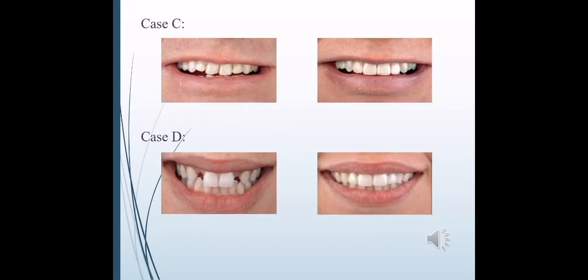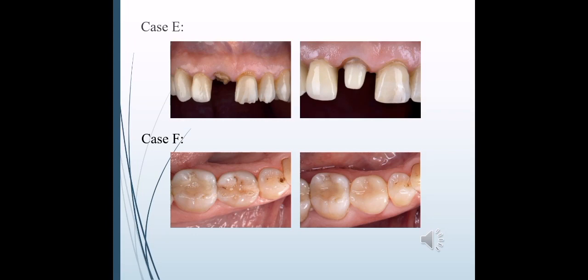They also have been used for developing form, contour, and incisal edge position, as seen in the case above, a preoperative view. Then on the right picture, we can see a postoperative view after being restored with Filtek Supreme Ultra. They are also used for resin bonded bridges, as we can see the patient having missing lateral incisors, and her bridges were bonded with opaque A1 shaded flowable composite, which is Genial Universal Flow initially, and then injected with B1 shaded flowable resin composite. They also have been used for developing post and core, as we can see in the picture on the left. There is a failed endodontically treated upper right central incisor that was restored with A2 shaded Genial Universal Flow. While in the next case we have a primary molar that was restored with an A3 shaded Genial Universal Flow.